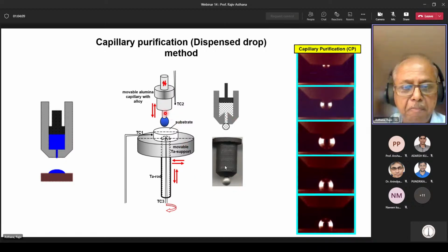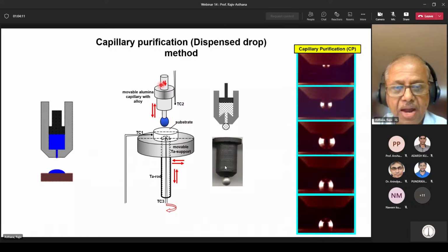So you heat the metal separately inside the vacuum chamber and you heat the substrate again separately in the same chamber. And at some specific time, you squeeze the liquid droplet, bring it in contact with the substrate. So this kind of a process does many things. One, it allows you to have an accurate estimate of time of contact of the liquid and the solid.